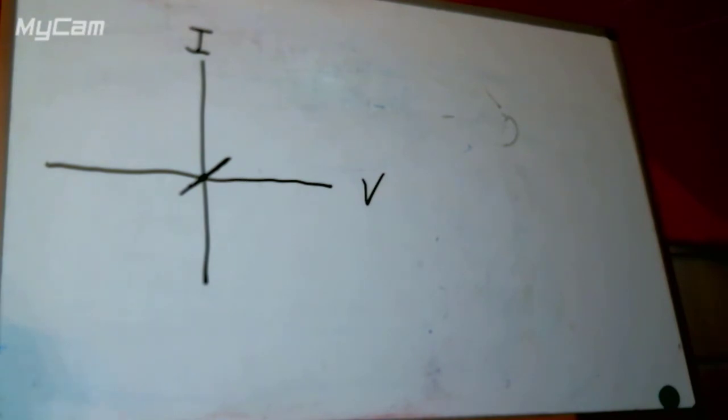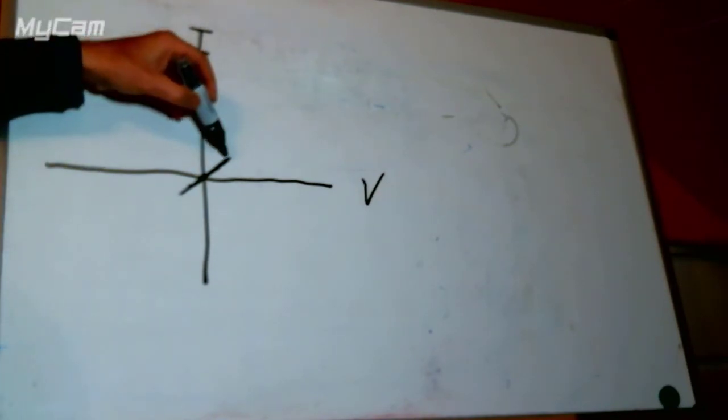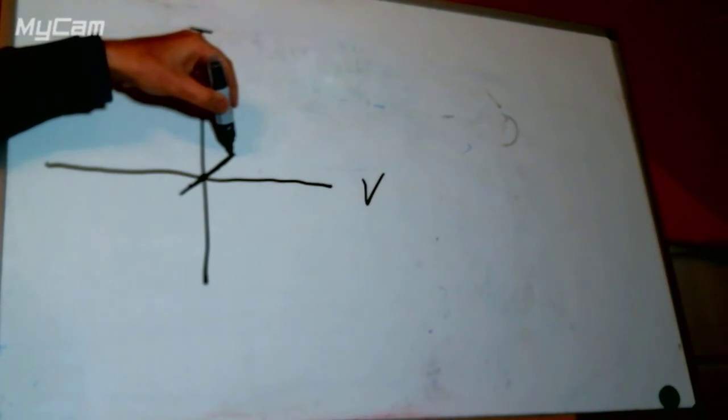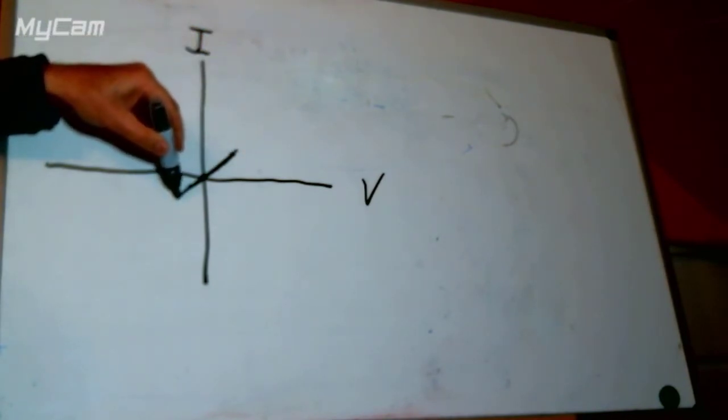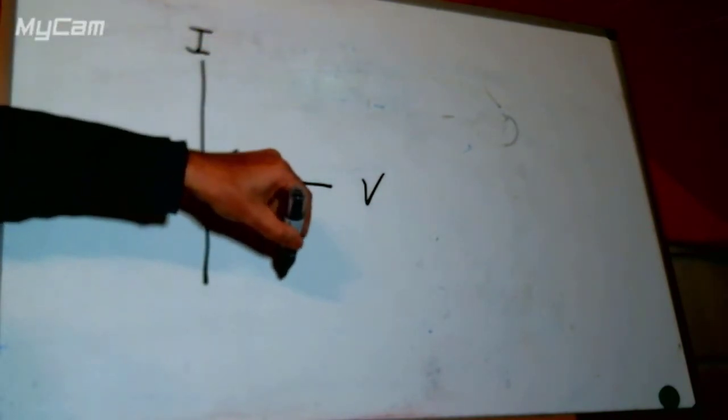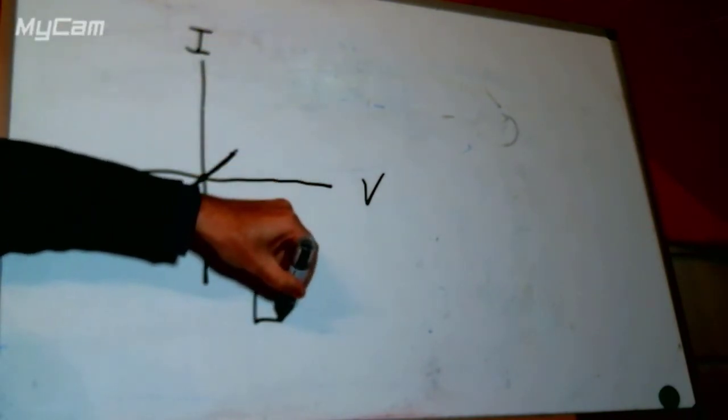As we increase the voltage, we will get more and more current, but it won't continue for very long, because eventually we will have the problem that we will not be able to get the copper ions away from our electrode. Or in this direction, it's also going to stop at some point, because we will use up the copper ions that are close to our electrode, and then there will be none.